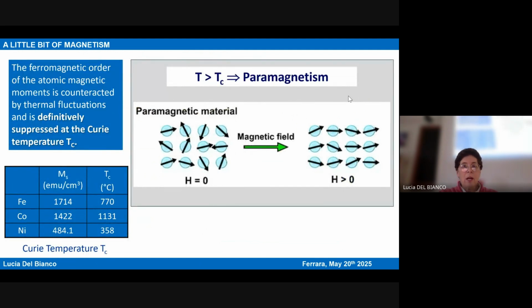Another important thing that I have to recall is that the ferromagnetic order of the atomic magnetic moments, namely the fact that they are all aligned, parallel aligned, is actually counteracted by thermal energy, therefore by thermal fluctuation. And therefore, a critical temperature exists, which is different for each type of ferromagnet, which is the Curie temperature, above which the ferromagnetic order is lost. Because the thermal energy is so high that the magnetic moments are free to flip back in any direction due to thermal fluctuation.